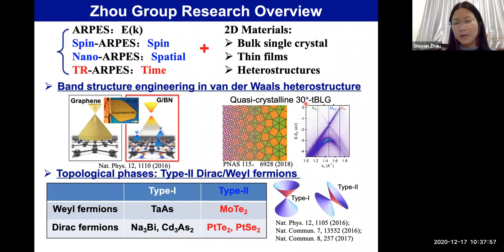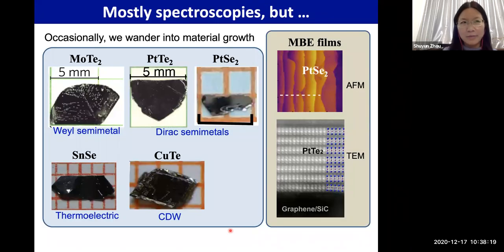We are also interested in topological properties of the band structure in layered materials, including this type-2 Weyl semimetal, molybdenum ditelluride, and also this type-2 Dirac semimetal, platinum ditelluride and platinum diselenide, and so on. Most of the time, my group focuses on electron spectroscopy, but occasionally we are also interested in material growth. For example, this molybdenum ditelluride and this platinum ditelluride, the samples were actually grown by my students.